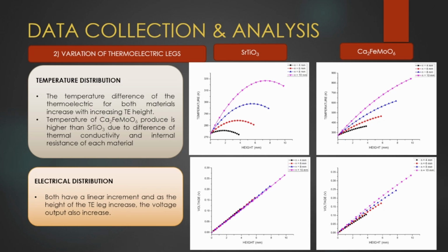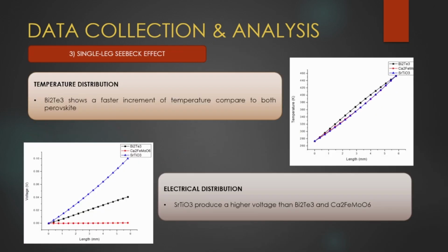Second is the variations of the thermoelectric legs, which is the optimization simulations. So the temperature distributions, as you can see for both materials, the temperature difference of the thermoelectric for both materials increases with increasing TE height, and the temperature of the Ca2FeMoO6 produced is higher than strontium titanate due to the difference of the thermal conductivity and the internal resistance of each material. For the electrical distributions, both have a linear increment, and as the height of the TE leg increases, the voltage output also increases.